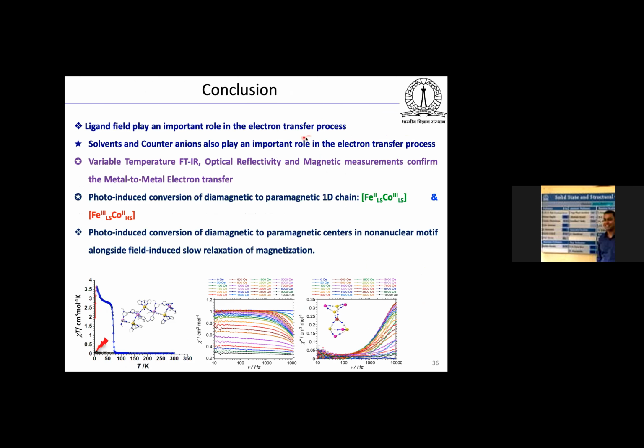So in conclusion, what we have observed is that the ligand field plays a very important role in the metal to metal electron transfer process, and the solvent and counter anion also play a very important role. By changing the solvent molecules in the matrix, you can tune the metal to metal electron transfer process. We have performed different optical reflectivity and magnetic measurements to confirm the metal to metal electron transfer process, and a photo-induced conversion of the diamagnetic to the paramagnetic state is also possible by using light radiation.